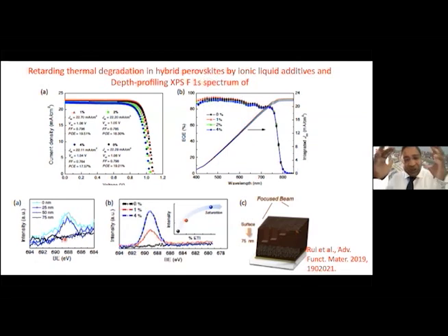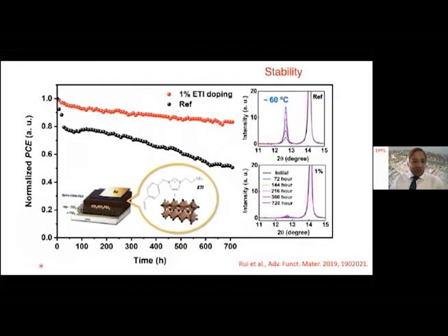So the information it gives you is that when we are mixing the perovskite with this ionic liquid, and the perovskite solution is DMSO or DMF, this fluorinated ionic liquid is floating and forming a shell on the top of grains and giving protection to the perovskite composition. So this is the take-home message. And now we have shown the stability data using the reference sample and the ionic liquid doped samples here, just as I showed before, up to 60 degrees temperature. This is a reference sample. You can see the formation of lead iodide. This 12.7 peak is a characteristic peak of the lead iodide.